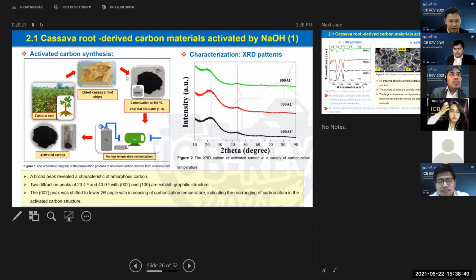And then we first carbonize it at 400 degrees Celsius. And at this temperature, we mix it with sodium hydroxide at a ratio of 1 to 3. And we do the carbonization at high temperature. In this work, we use 600, 700, and 800 degrees Celsius. So after this, we can obtain the activated carbon. The color is black, of course.